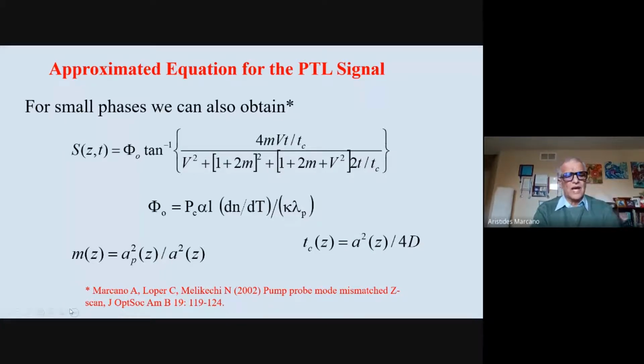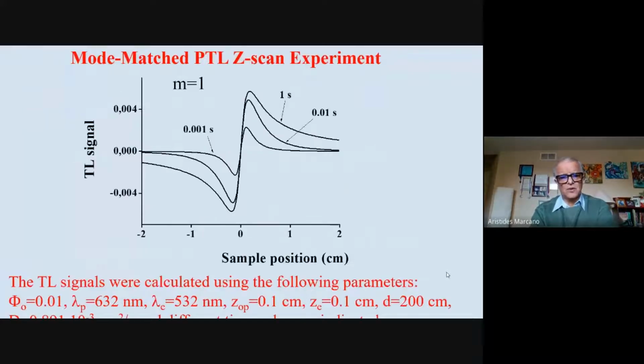And here is the factor M, which they call the mode mismatch factor, that gives the relation between the radius of the probe beam divided by the radius of the pump beam. And again, we have this thermal buildup signal. The time dependence of the signal will give you the diffusivity of the sample, and the amplitude of that will give you the absorption coefficient if you want, or other parameters. This is the calculation you can do using this formula.